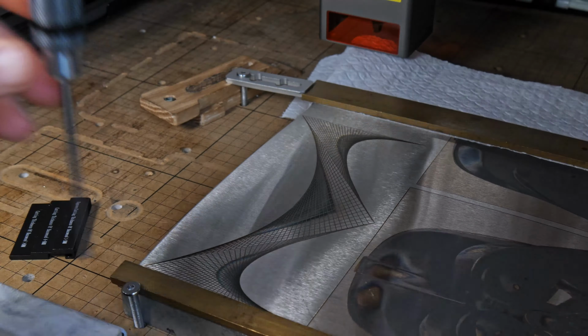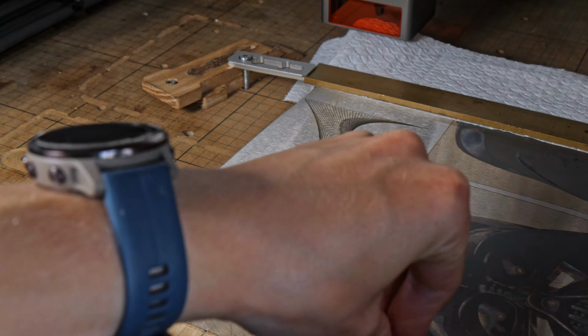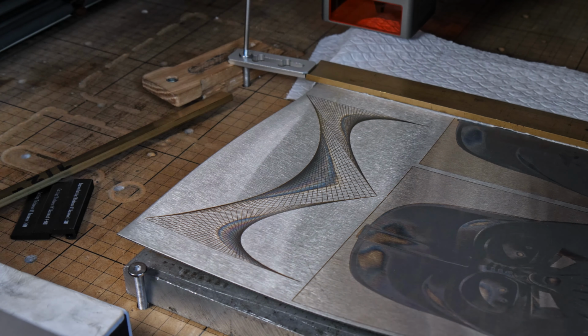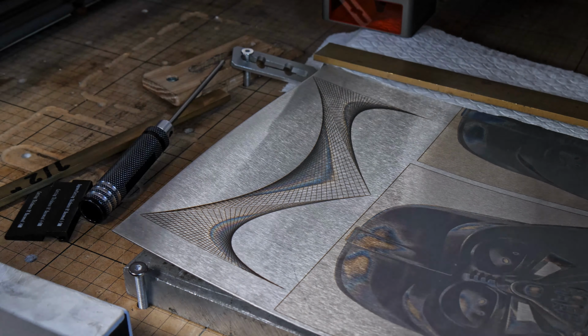I think initially the colours look quite nice, but you can see even despite the clamping that I've done, the thin 0.7mm stainless steel has warped fairly significantly. Just flipping between before and after I'd done the final lines, you can see a big difference in the surface of the sheet metal. That's because so much heat is getting dumped straight into the surface from the laser. Despite the warpage, the main aim to experiment with the gradient fill came out pretty well. I quite like the colours, although they haven't come out quite as vibrant as I would have liked.